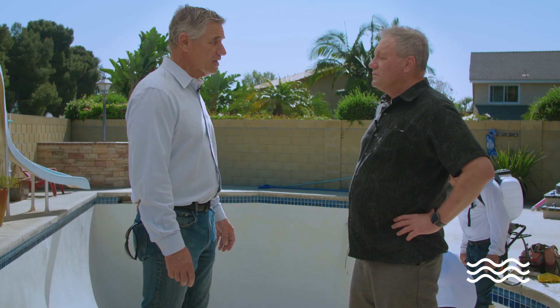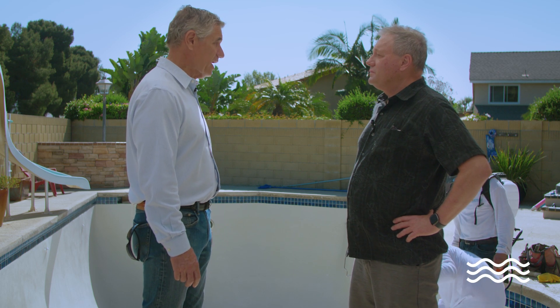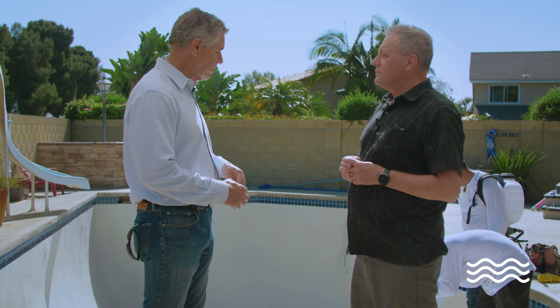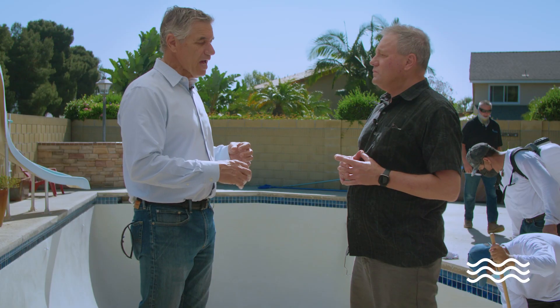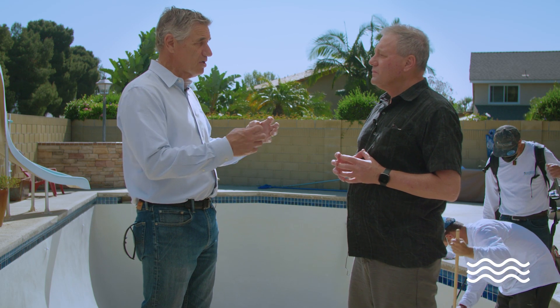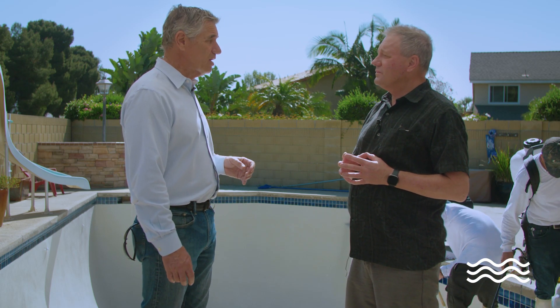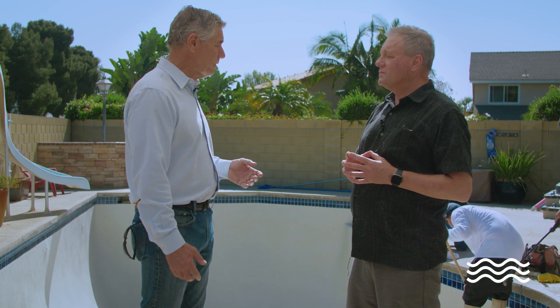There's a very interesting technology on the deep penetration side that's a little different than this. We don't need deep penetration on a half inch of plaster — we just need to get maybe the top quarter inch and you're done. Where concrete has structural issues, it's a little bit different. But this is called Micro Glass — it's a fantastic product, it's a game changer for everybody. Also it really helps lock the color in too, because pigments are very small particles. And when any type of cement is attacked with water — especially aggressive water — it starts bringing the calcium hydroxide out. But it's not the perfect everything; there are limitations. If you still have extremely aggressive water, eventually nothing's completely impenetrable.